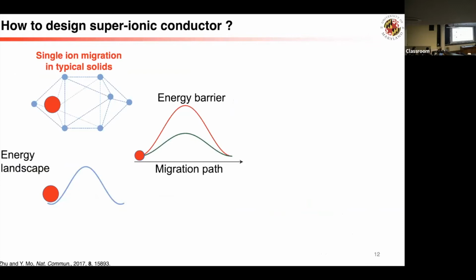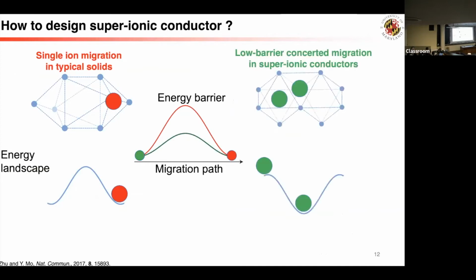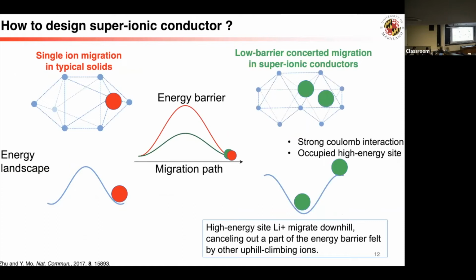So with that, I think this gives a good understanding. In a typical solid, you have ions jump from one site to the other, and you have this high barrier. In super-ionic conductors, usually ions occupy both high sites and low sites, and when they migrate, they have this concerted migration mechanism. So these move down while those climb the hill, and this canceling gives a lower barrier. So with that, I think we have a very good physical understanding of why these certain classes of materials work so well, giving such a low barrier and a high conductivity.